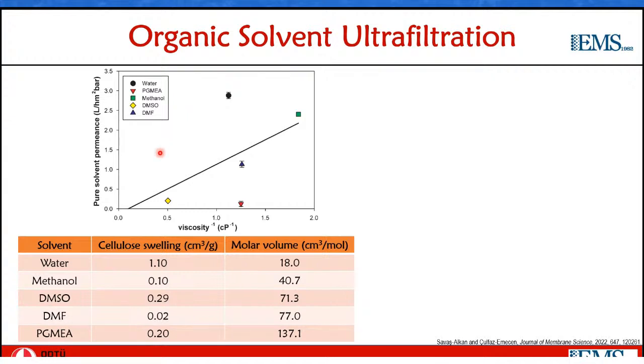So when you consider ultrafiltration membranes, what you expect to observe is pore flow of solvents through these membranes, and then the permeance would be expected to scale linearly with the inverse of the solvent viscosity, as simply expected from the Hagen-Poiseuille equation. When we plotted the solvent permeance as a function of the inverse of viscosity for these 5 solvents, we do see a trend, but the water permeance is much higher above this trend, and the PGMEA permeance is much lower.